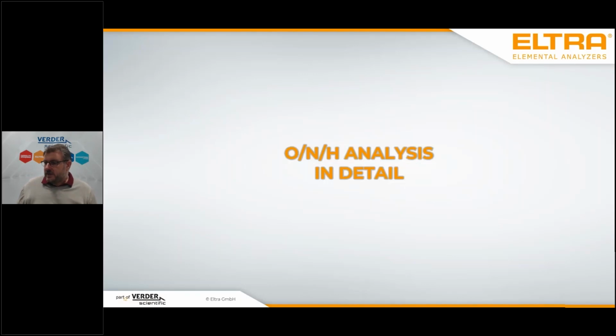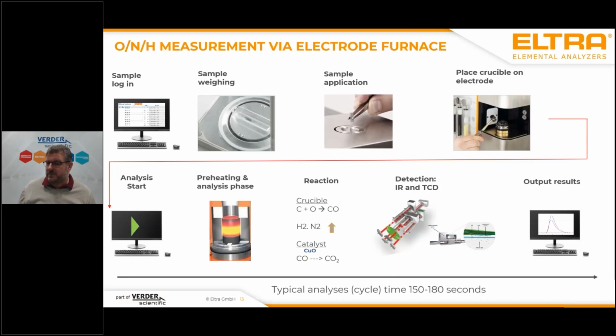ONH analysis is a little bit different. This is just due to the fact that you have to remove oxygen and nitrogen, which is really present in our atmosphere in a large amount. Because on the one hand, you log in the sample again, weigh your sample, apply the sample, but then you have to apply it to a sample port, which can be flushed with inert gas like helium. Then again, you start analysis.